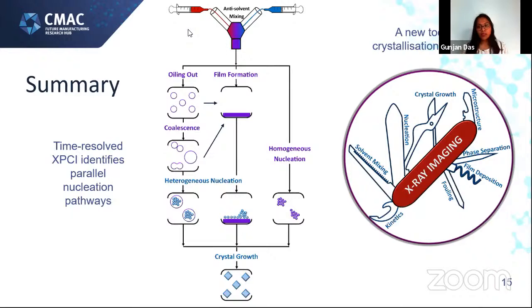Another thing I would like to mention is X-ray imaging is an extremely powerful tool, just like a Swiss Army tool, because while we're taking imaging, we're able to obtain a number of pieces of information while taking one single scan or doing one single crystallization study. While we're watching, we could see nucleation, crystal growth, we could observe the microstructure, phase separation, film deposition, solvent mixing, and kinetics.